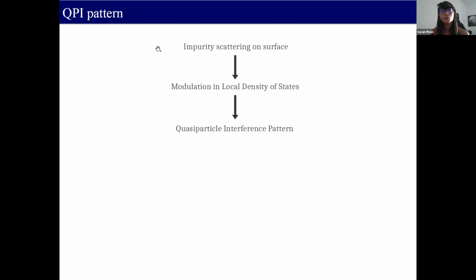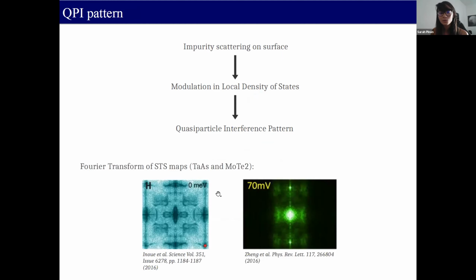So if we have impurities on the surface, this will cause scattering, and this is seen as a modulation in the local density of states. Now, if we go to k-space, we see what we call quasi-particle interference patterns. So these are two examples of QPI patterns that can be obtained experimentally. What you need to do is to take the Fourier transform of STS maps. So here we have two examples of two different Weyl semimetals. Here on the left, we have a QPI for TaAs, and here on the right, we have one for MoTe2.